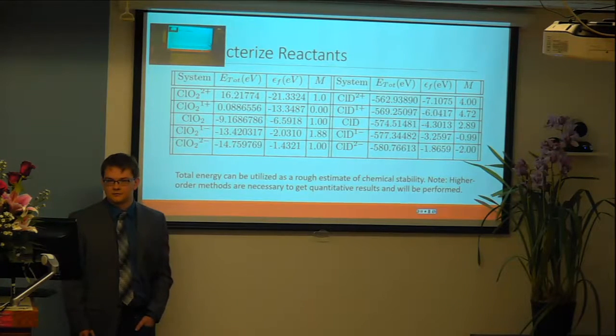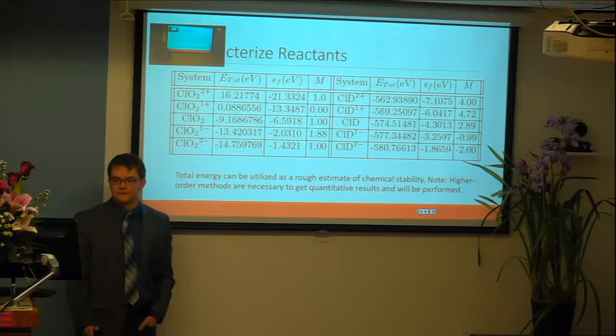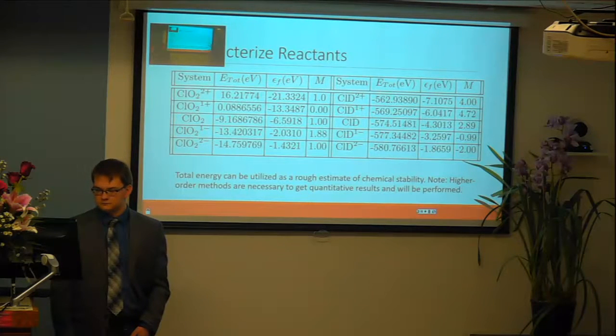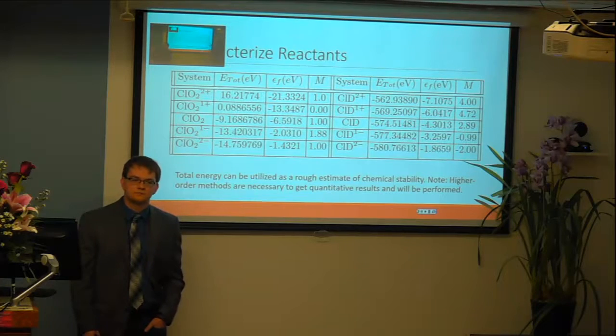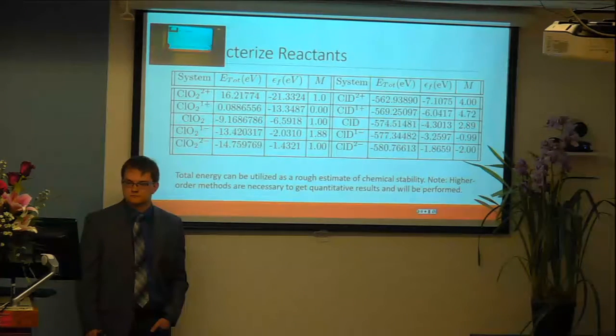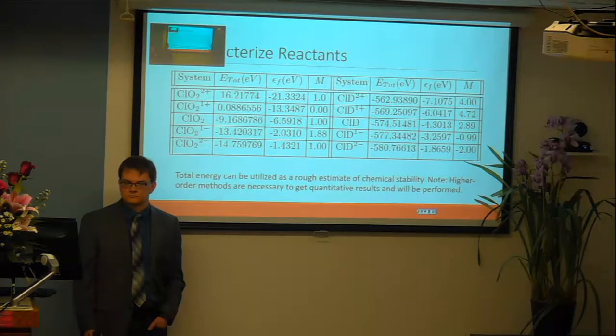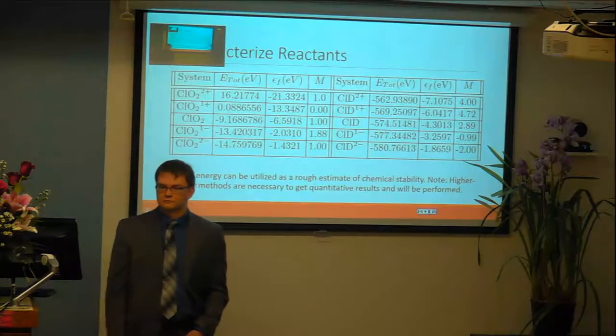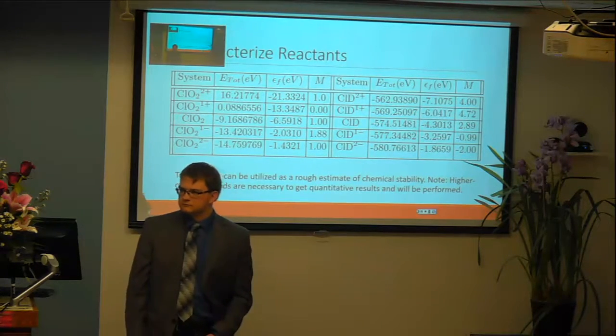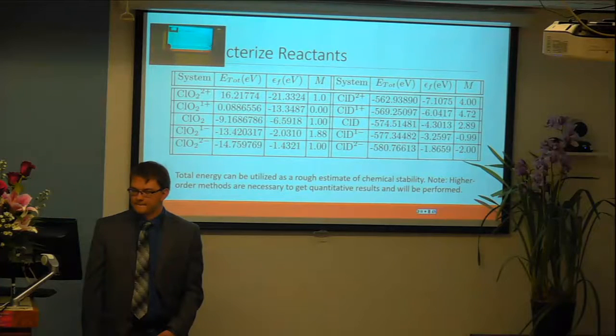The electron has to come from somewhere, right? So if you add an electron directly to any system, the total energy is always going to go down, always going to become more negative. And that's what you're seeing here, right? As you reduce, the number always goes down. It doesn't matter what the orbital energies are, because even if the orbital energy were too high, the electron will just float around, not bound to anything, and the electron energy will still become more negative. So that electron has to come from somewhere, so you need to balance it out by having a corresponding oxidation somewhere else.